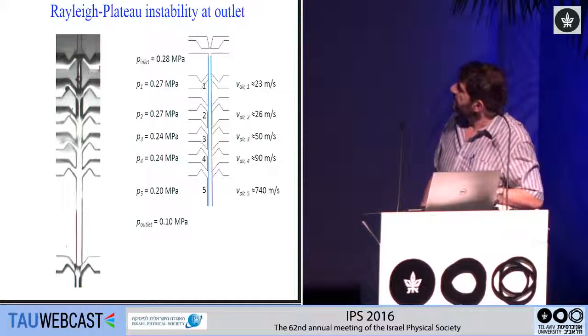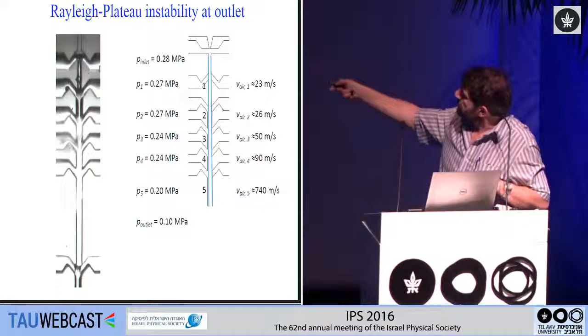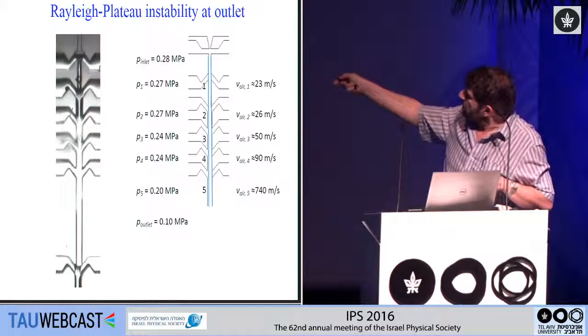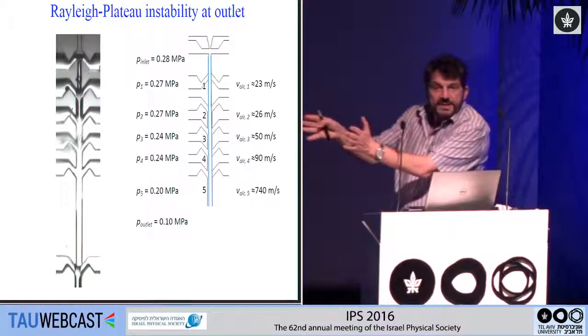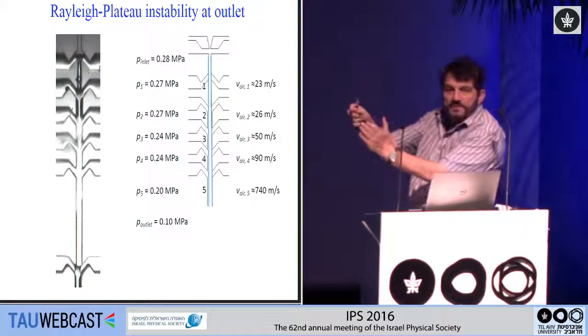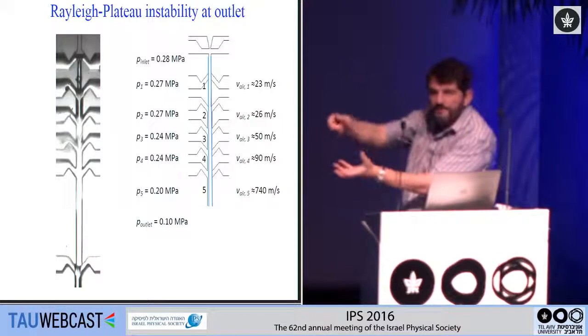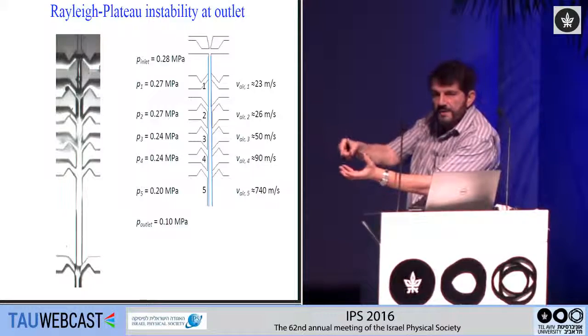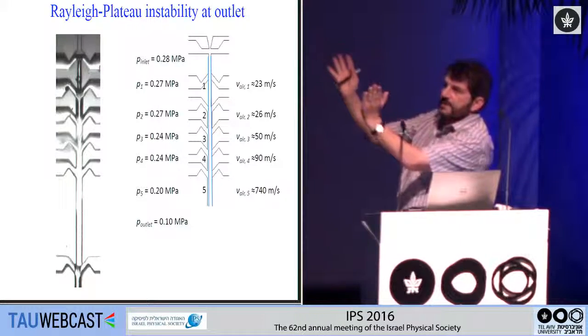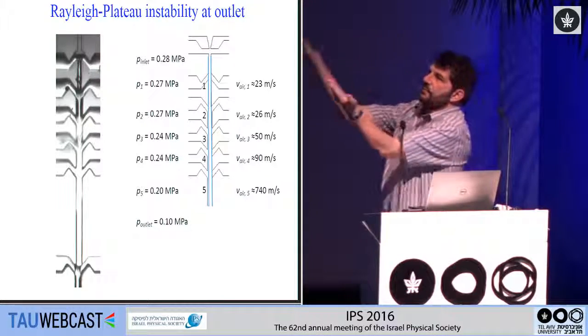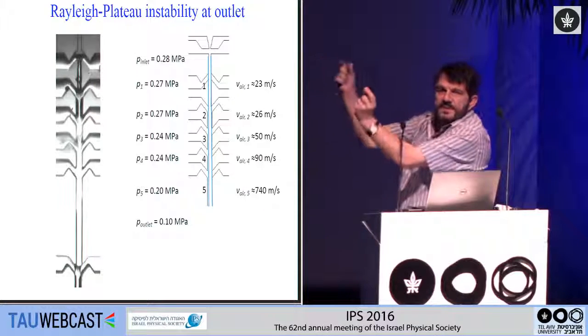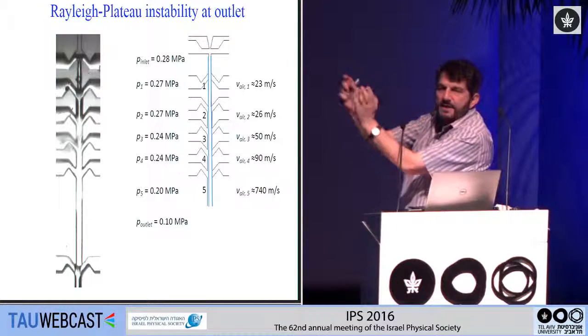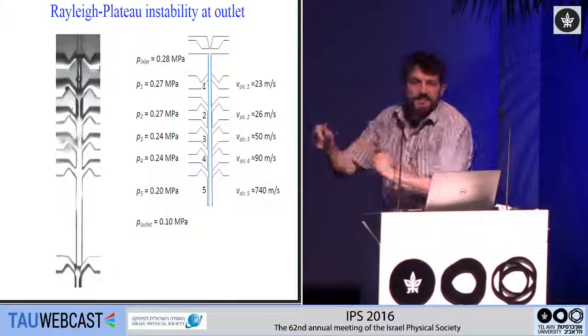I won't go through the details of this. Essentially, what you do is you get a very thin film that coats the side, and then it breaks. Imagine if you've ever seen these pictures where something falls on the surface of water, and you get a plume that comes up, and you get a ring, and then it breaks into drops. The same kind of phenomenon is happening here. You have a very thin ring, and it's breaking into drops.